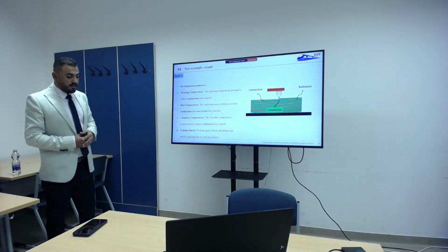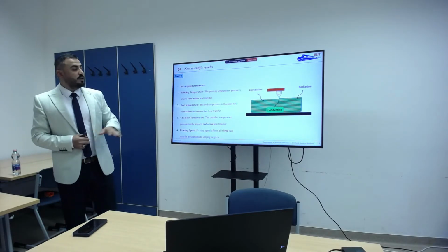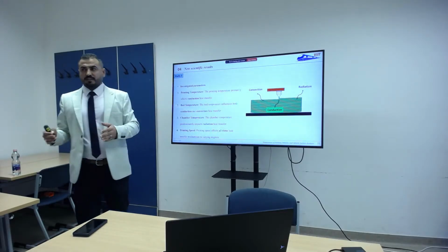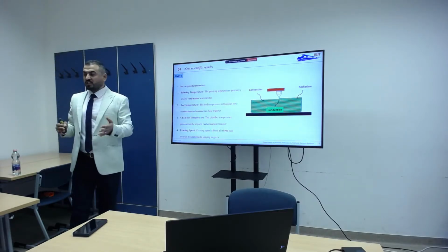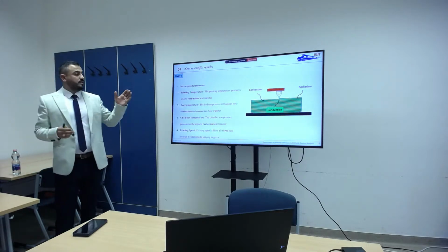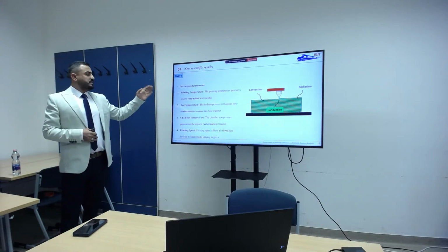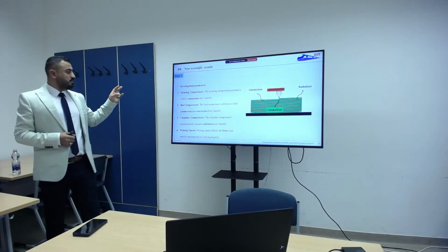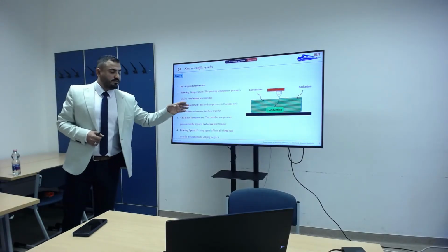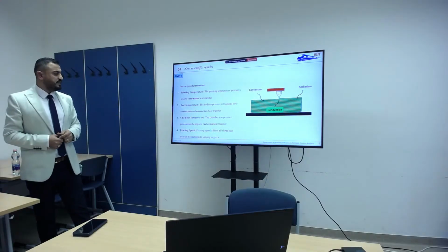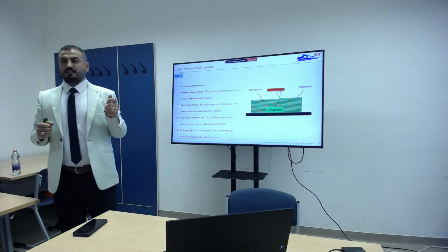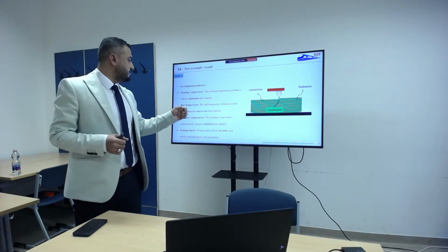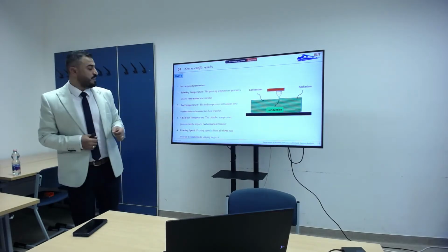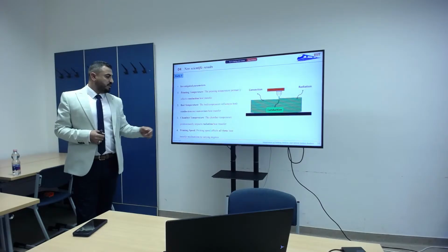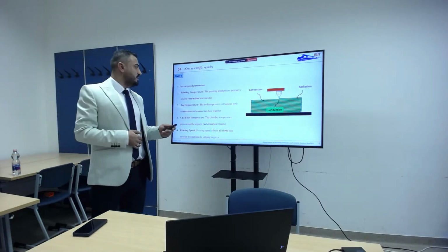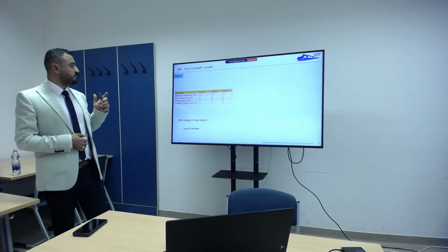For the second study, I investigated the thermal parameters. As we know, heat can be transferred through 3 mechanisms: convection, conduction, and radiation. So for the conduction heat transfer, I investigated the printing temperature, also the bed temperature because it controls the convection and conduction heat transfer, and I investigated the chamber temperature because it affects the radiation heat transfer, and printing speed because it affects all 3 heat transfer mechanisms.